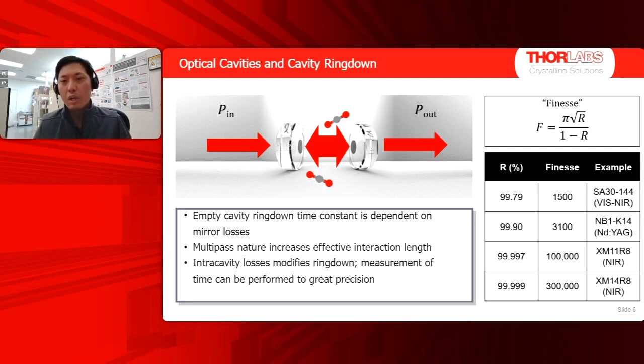And to orient you, we have the scanning Fabry-Perot interferometers, the SA30-144, a visible to near IR interferometer that has mirrors with reflectivity of 99.79%, and that's a finesse of 1500. 99.90% reflectivity gives you a finesse of about 3000, and that's like a laser line mirror.